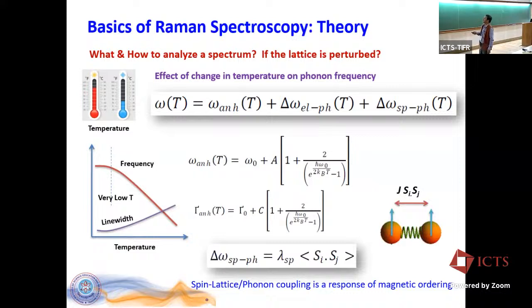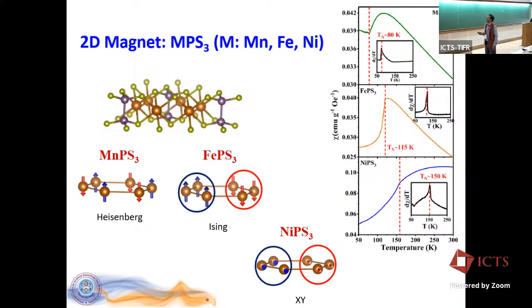And okay, spin-phonon coupling basically can be understood as a spin-spin interaction, and there is a factor, which is the spin-phonon coupling coefficient or constant, and that's what helps us to quantify it to a certain extent.